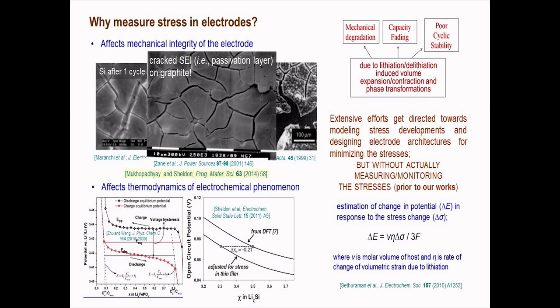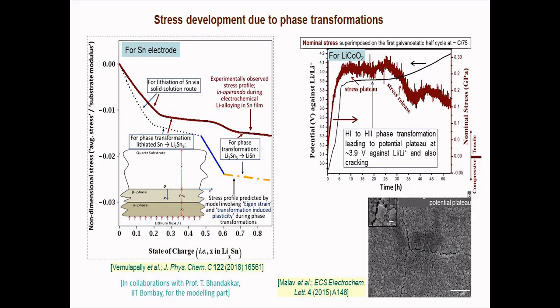It leads to cracking and disintegration of the electrode. Not just that, there is a passivation layer which forms on top of the electrode material, and it also can get cracked due to the stress development. It affects the thermodynamics and it increases the voltage hysteresis, which negatively affects the efficiency with which the energy can be stored and released. So it is extremely important to monitor the stress development in the electrode materials, if possible in real time during the electrochemical cycling, and that is one of the things we do.